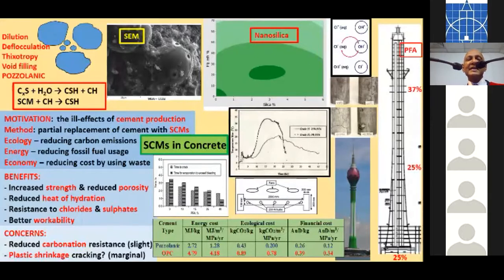The cement particles gain strength when the water reacts with the surface of the cement particle. Now, sometimes these cement particles can tend to stick together, but if smaller particles go in between them, they get deflocculated. So it exposes the surface of the cement particles for the hydration to take place. Because these particles are circular in shape, it creates a ball bearing type of effect and makes a concrete mix more workable. So that's called a thixotropic effect. And also it fills in the voids, causing the whole structure, the concrete matrix, to be more compact, and also less water to be used in the production of cement. And if you use less water, the concrete will have higher strength. Above all, it has what is called the pozzolanic effect.